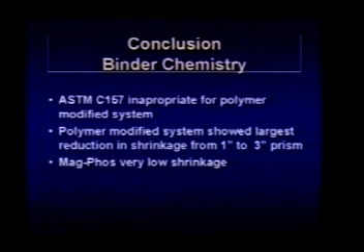Some conclusions we can make about the binder chemistry. We saw that the C157 test method was inappropriate for the polymer modified system because it expanded so much during the first 28 days. So the value we would purport would look very good because it would come back down to 0, but we see the important factor, which is the gross shrinkage, was very high.